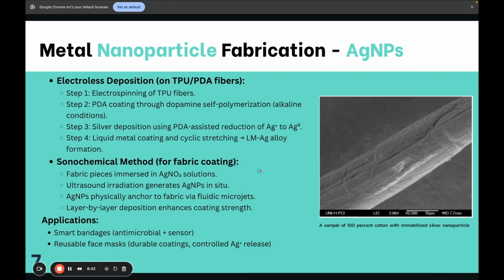Then comes the sonochemical method for fabric coating, in which spunbond fabrics are cut into 2 by 2 centimeter square pieces. They are immersed in silver nitrate solutions. Ultrasonic waves are applied for 25 or 50 minutes. This causes silver nanoparticles to form directly within the solution where the fabric was immersed. This actually creates high-speed microjets that anchor silver nanoparticles onto the fabric. Then, layer by layer deposition takes place to enhance coating strength. If there are more silver particles, there is a stronger coating, plus better durability.